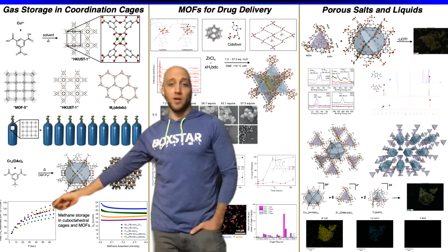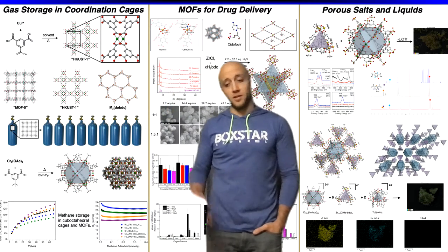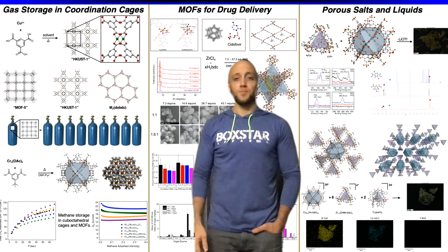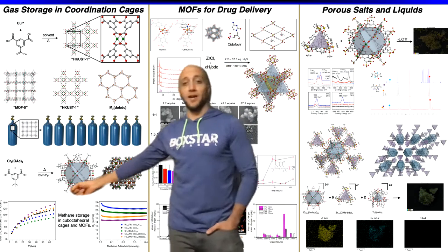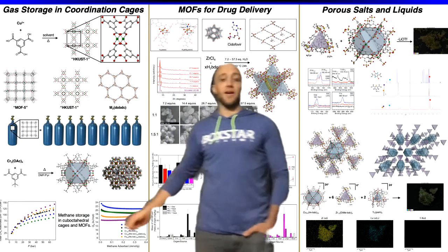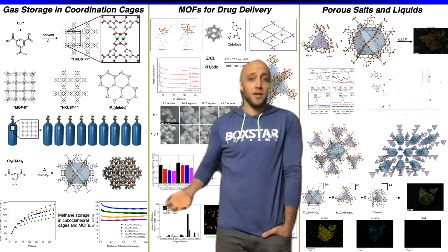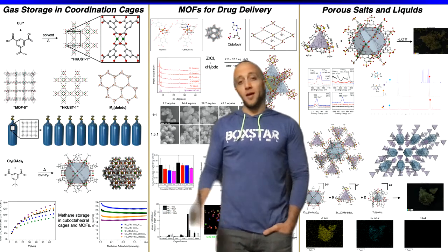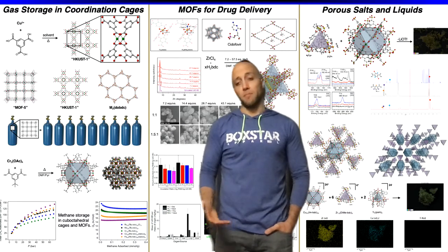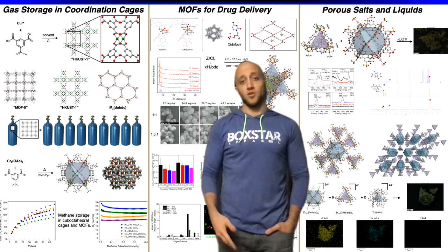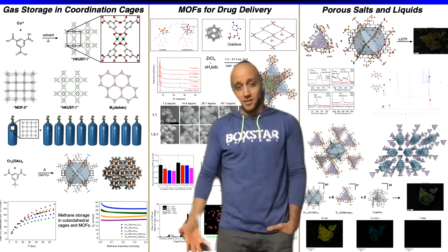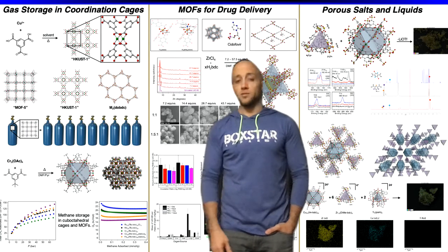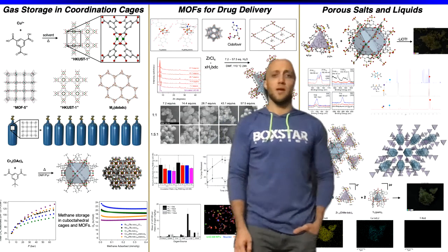So shown on the bottom here, my group very commonly measures gas absorption properties. So we measure a lot of isotherms. Here it's showing that the methane uptake at room temperature and 65 bar is as good as many three-dimensional non-molecular solids. So they're very interesting from a storage standpoint, but because they're molecules, they're easier to make, easier to characterize, you can purify them, they're a lot more processable. So we're really excited to push the boundaries of gas absorption for storage or separations for these new materials.